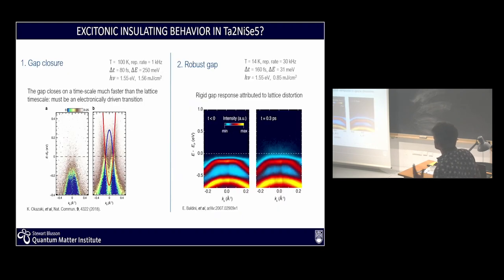There has been nice time resolved ARPES work by a number of groups, and if you compare these 2 results, one is in favor of a gap closure due to the photodoping, suggesting that the transition is electronic in nature. The other one is in favor of a robust gap, suggesting the transition is structural. One key thing to keep an eye on here is the fluences used for the pump, 1.5 millijoule, and half of that fluence here. So certainly there is a fluence dependence, which is important. In any case, the question is still open. Is the gap of electronic or structural nature?